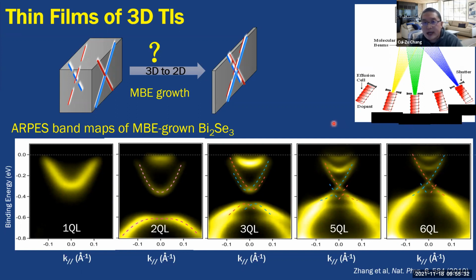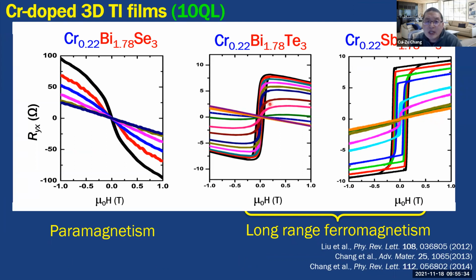This is the first step. The second step is that we need to introduce ferromagnetic order. As you may know, there are 3 members in the bismuth selenide family of topological insulators: bismuth selenide, bismuth telluride, and antimony telluride. We tried very hard with all the transition metals in the periodic table and found chromium to be the best candidate. So we doped chromium in these 3 topological insulators, and in chromium doped bismuth selenide, there is no hysteresis.